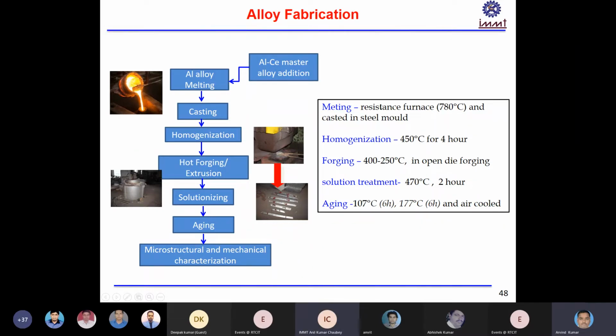We have done the melting at around 780 degrees temperature and cast this alloy, homogenized for 4 hours. For forging we heated the sample to 400 degrees, and then forging was done. Forging actually continued down to 250 degrees, so in this range, 400 to 250 degrees, the open die forging was done. You can see here the press and the samples being forged, and finally after forging you get this shape. Then solutionizing at 470 degrees for 2 hours, and then aging. Actually, we have done double aging: 107 degrees for 6 hours, then 177 for 6 hours, and then air cooled.